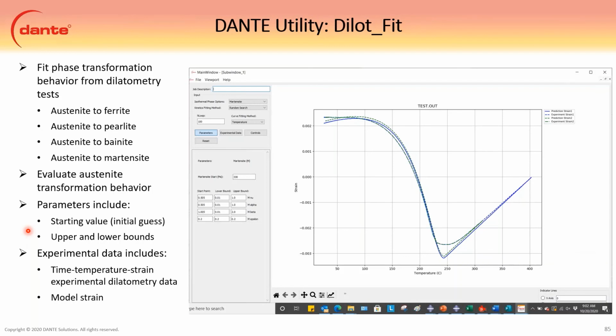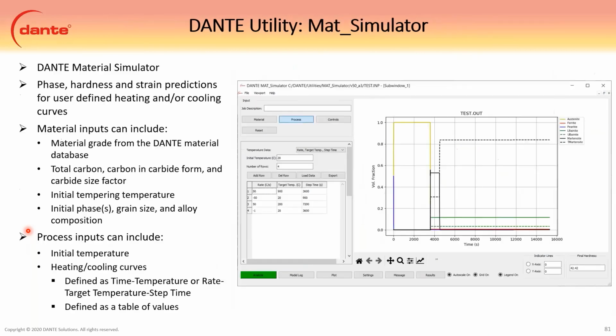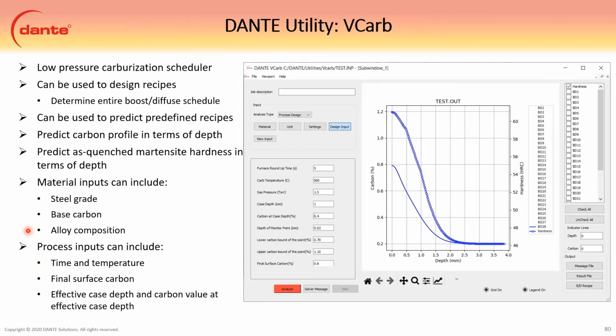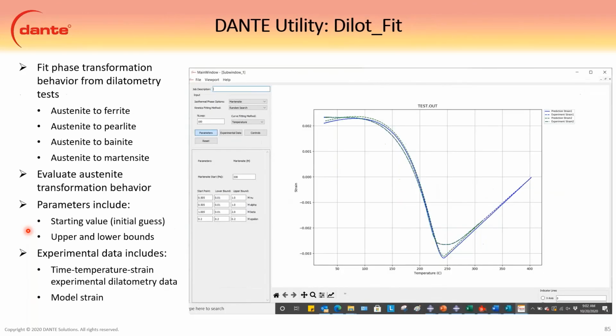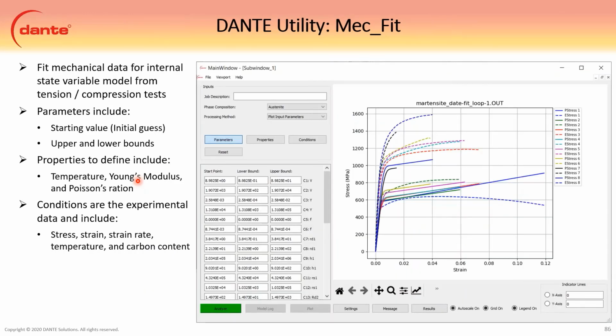These last ones are fitting tools. So the previous ones can all essentially be used on their own without Dante. However, the fitting tools don't make any sense unless you have Dante because they fit material test data to our model parameters. All right, so Dilot_Fit takes dilatometry data and fits the austenite transformation to all the diffusive phases and the martensitic phases. MechFit takes standard compression and tension tests and fits them to our internal state variable model.